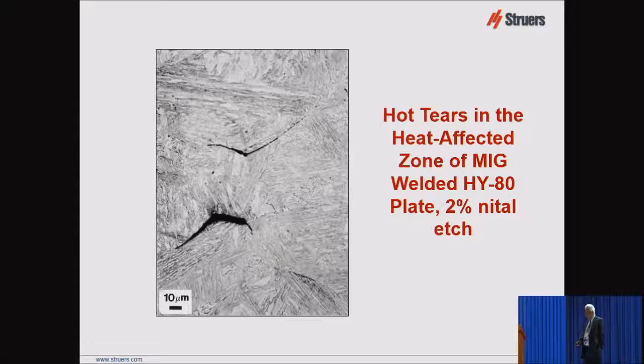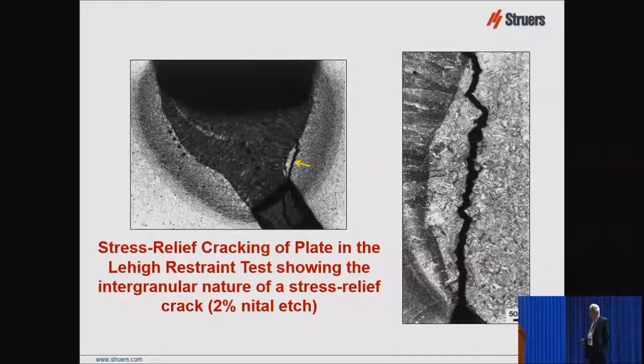Here's a hot tear in the heat affected zone of a metal inert gas welded HY80 plate steel, high strength plate steel etched with Nital. And you can see the cracks, they're in grain boundaries. This is a stress relief cracking in a test developed at Lehigh University called the Lehigh Restraint Test in the literature.